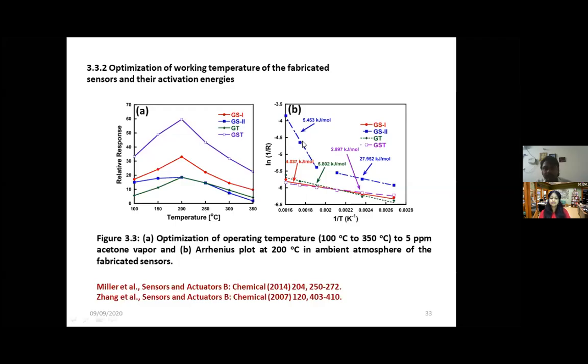And similarly, this is for GS2. This is the activation energy of SnO2 separately and graphene oxide separately. However, for GS1, the red curve here, it is 4.037 kilojoules per mole, but the average of these two is 16 kilojoules per mole. So the activation energy of GS2 is way beyond GS1, and hence the difference in response between these two materials.